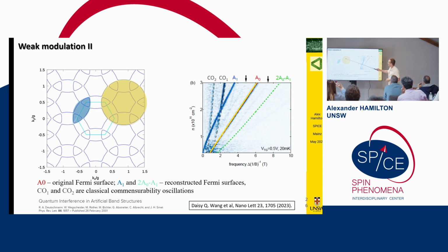Then there's this Fermi surface here, which is caused by the intersection of the first two Fermi surfaces where they're repeated across. And that has a much smaller frequency. That's this line here. And these solid lines are fits just to a calculation of, knowing the periodicity of the lattice, that's the only parameter we have, and the density, I can immediately calculate what these frequencies should be, and so the solid lines are those calculations.